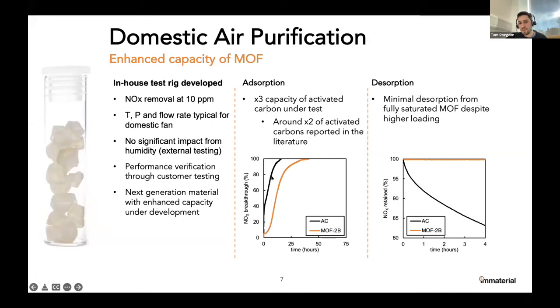The 3 times capacity that we've seen here, we went to the academic literature as well to try and understand, is it just that specific activated carbon from that product that isn't as good? Are there other things out there? It's very difficult to compare our test results to what you're seeing in the academic literature, because you need all of the conditions to match up. So with a fair caveat that it's hard to compare, from what we could see in the literature, we think we've got about 2 times the capacity of other activated carbons that are being tested in the academic literature.